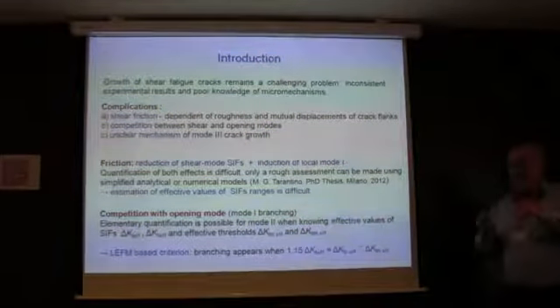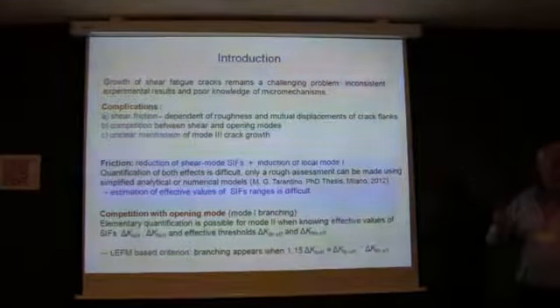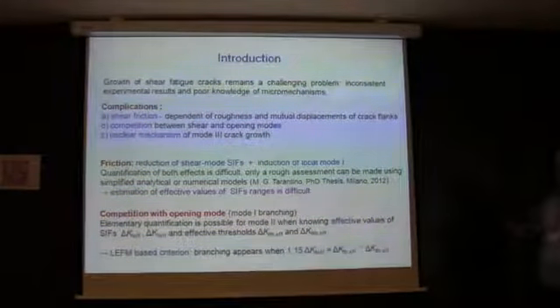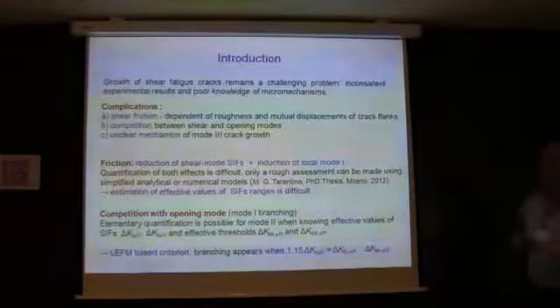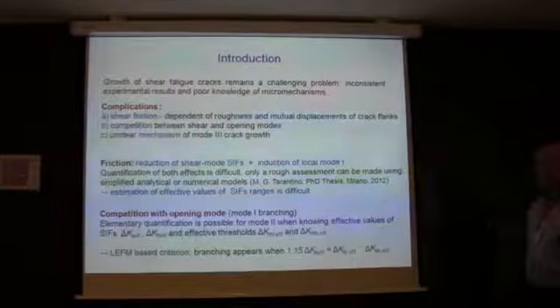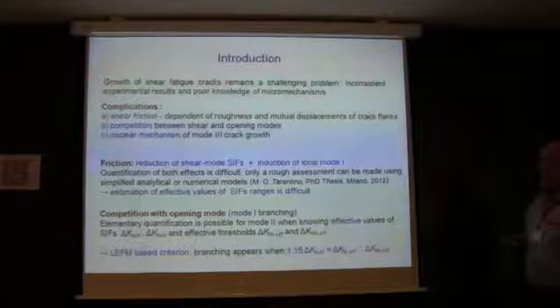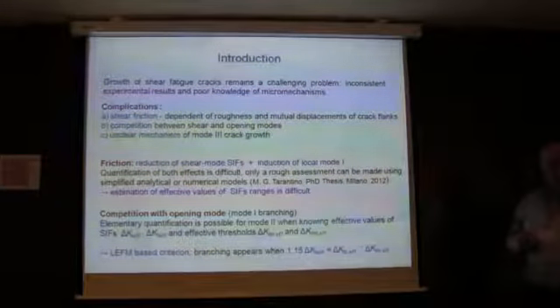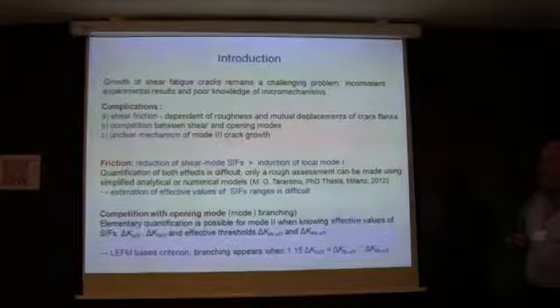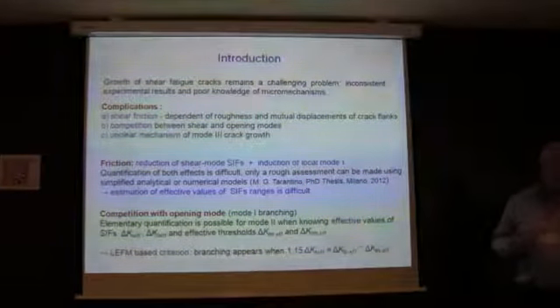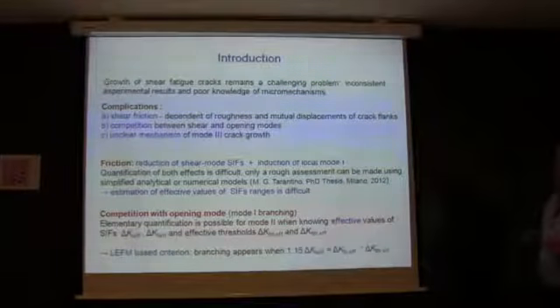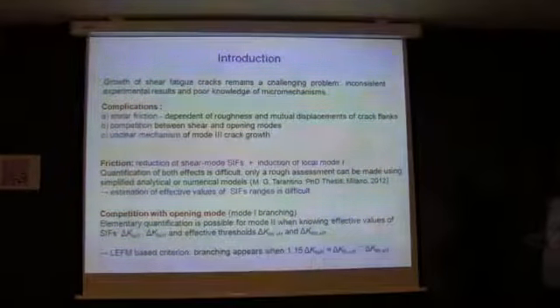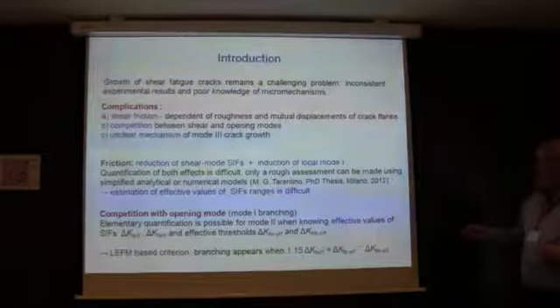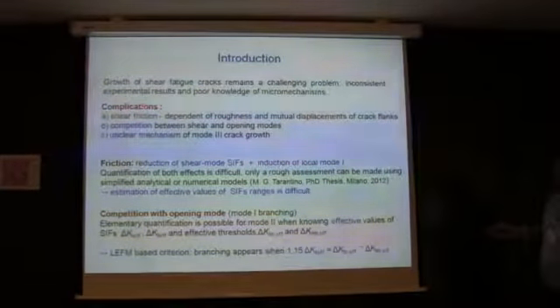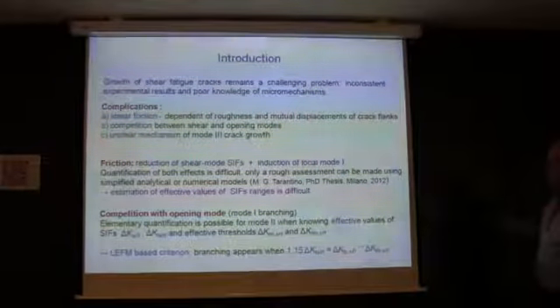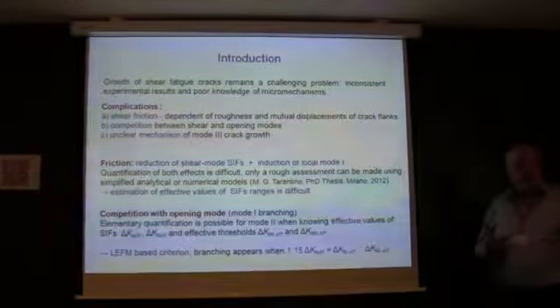Many things were done for mode 1 cracks and fatigue cracks and for closure, but not so much was done about shear cracks. The reasons may be some complications, more or less stronger than in the mode 1 case. First, there is shear friction, of course, which depends on roughness and mutual displacement of the crack flanks, material and so on, many parameters.